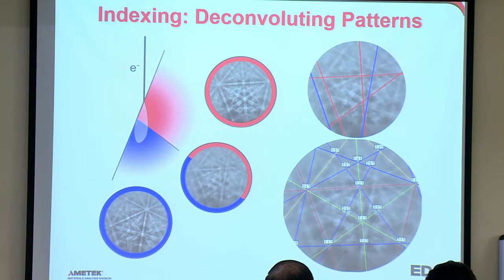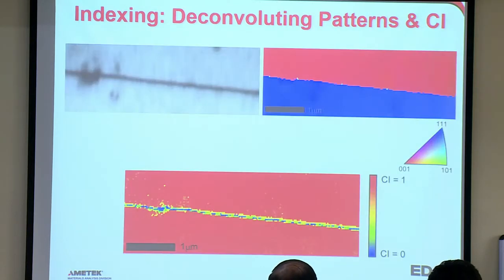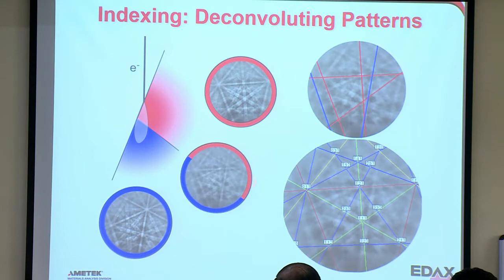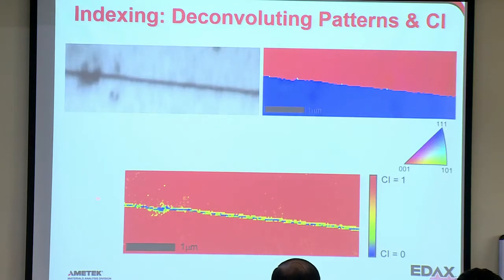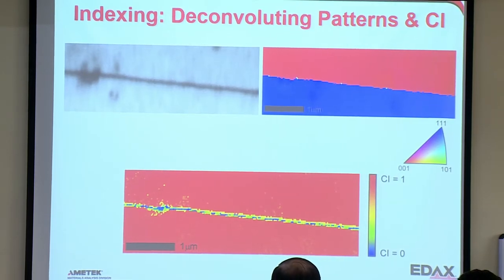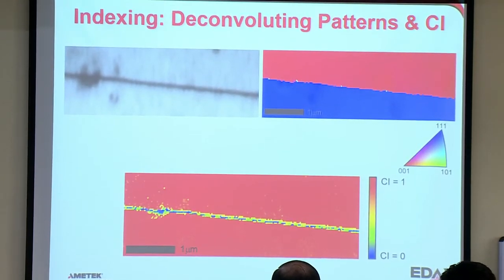I already mentioned the deconvoluting patterns, and you can see this effect in the confidence index. So this is the confidence index here. Now, when you have mixed patterns, you have two solutions competing, and so your votes will be affected by that. And so here, you see the confidence index at the boundary edge is 0, even though really we've only missed 1, 2, 3, 4, 5, 6 points. Our confidence index drops. And we have ways of dealing with that in the software.